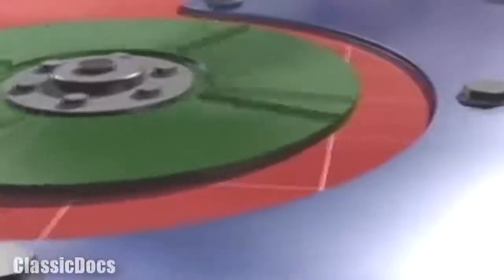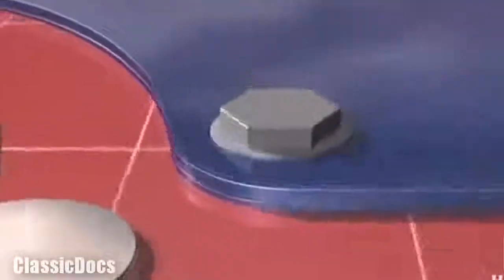A horizontal wheel with a grooved edge rotates near a curved section of steel with a corresponding groove. The blank spins into the channel, which grows progressively narrower. When the channel becomes narrower than the blank itself, the blank flattens at its edge. That raised rim helps pre-form the blank so that when it's struck into a coin, we get better fill and better appearance of the overall coin.